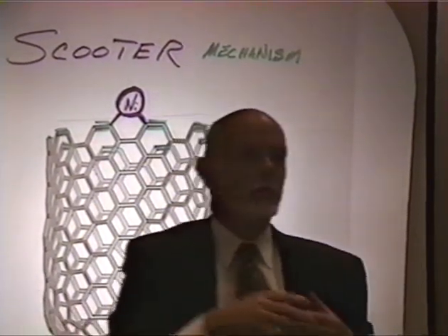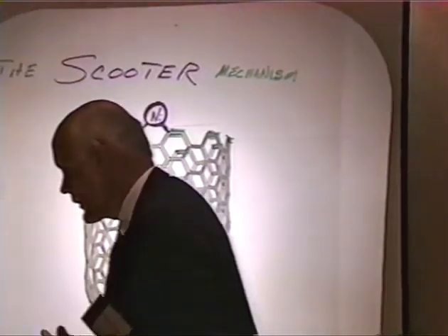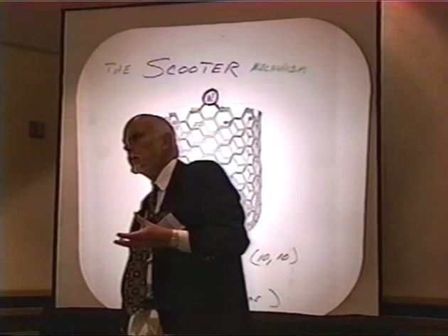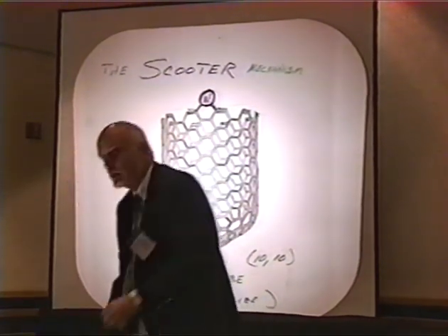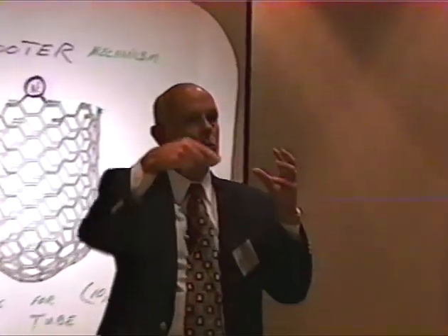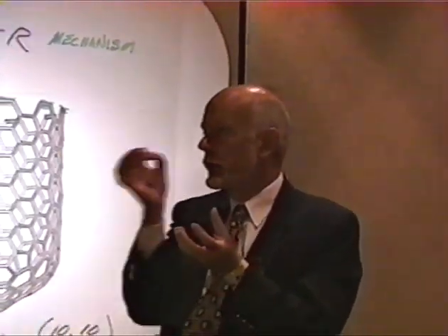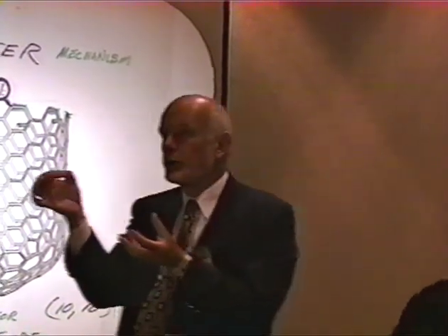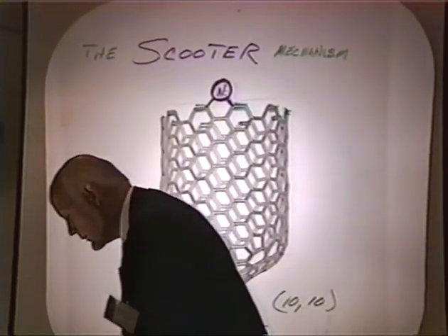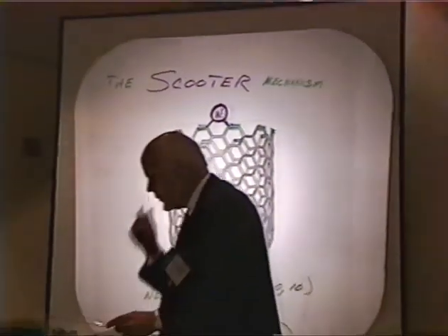And then the theory goes on that, well, if the temperature's hot enough and there's enough time, this little tublet, which has 1 or 2 or 3 metal atoms on the end covering and keeping it open, can relax and rearrange to the most energetically favored tublet, and there will be one tube that will be most favored. And we believe, and the calculations confirm, that that should be the 10,10 tublet. And if it isn't 10,10, it should be a tube that's close to that in diameter. And if it isn't perfectly this armchair edge, which allows you to make triple bonds all around that edge and lower the edge energy, it'll be something that's close to that. Just a few exceptions to just the size. And that seems to be consistent with what's seen.